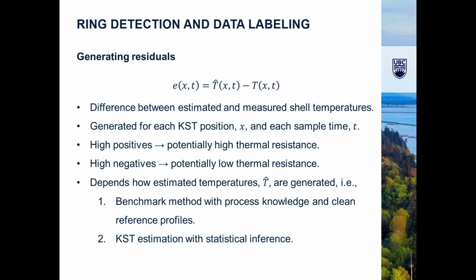Our approach to ring detection involves generating residuals. Residuals are the difference between estimated and measured shell temperatures. A residual value is generated for each kiln shell temperature position, denoted by X, and each sample time, denoted by T. Consider a kiln that is operating at a relatively steady state with respect to the energy balance. In this case, high positive residuals potentially correspond to a higher than expected radial thermal resistance, while high negative residuals potentially correspond to a lower than expected radial thermal resistance.